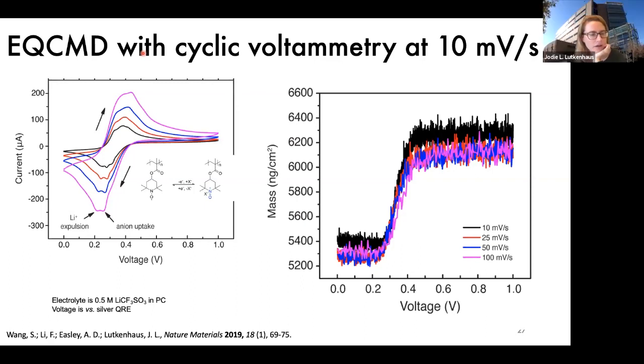Yeah, sure. I think I'm going to do some guessing here. So first, with the EQCM-D, this is a pure polymer film. We cannot have carbon additive in the sample because it will invalidate the measurement due to the dimensions and everything. And we need the film to be totally smooth. So this is a representation of what the pure polymer film is doing. Does this translate to the battery platform where you have a lot of carbon additive? I can't say. I'm not sure, because with the carbon additive, you now have interactions between the polymer and the carbon, and I think it's much more complicated than that. So if you don't see it in the battery platform, I wouldn't worry. It doesn't mean you did it wrong or anything. It's just a different environment. It may not be happening.